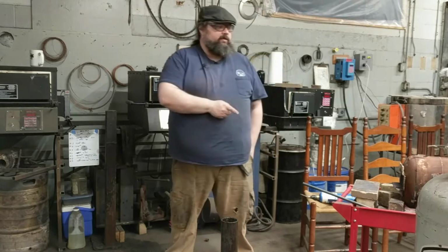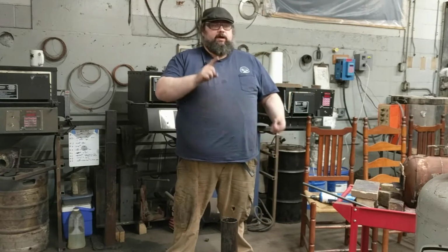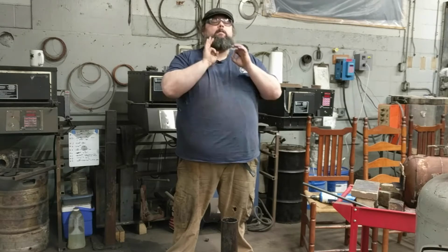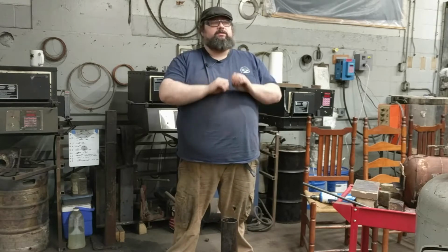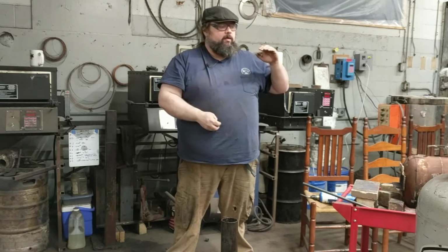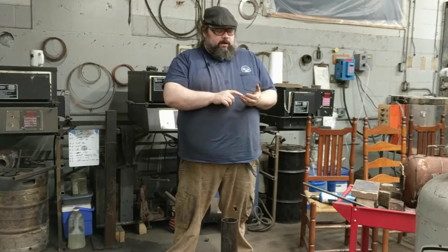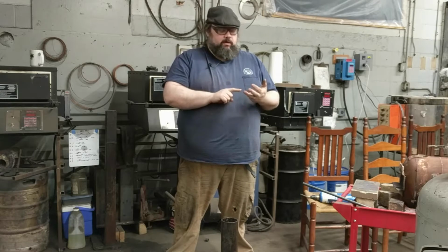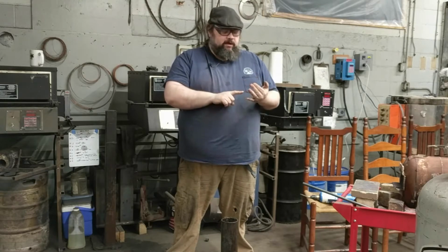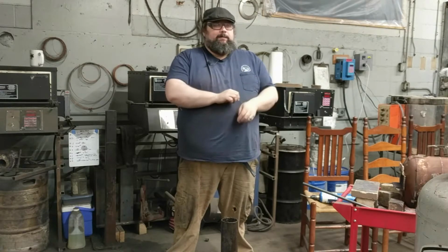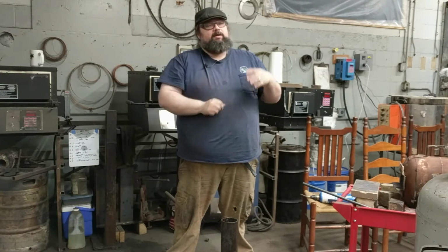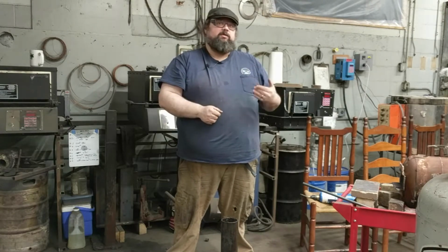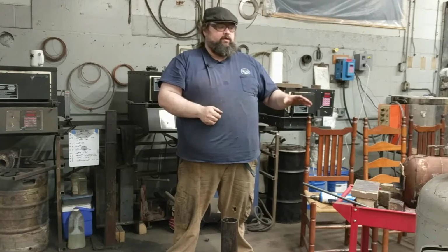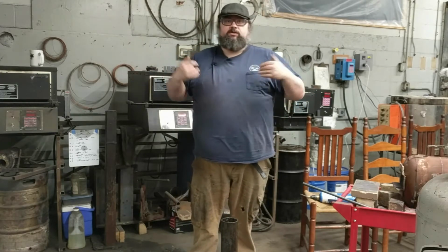Steels you want to stick with if you're going to heat treat in a forge: 1080, 1084, perfect. Those steels are simple heat treat, and they work amazing in a forge. Beyond that, you can do steels like 80CrV2 or 5160, 9260, and even steels that are pretty high carbon but have a very simple chemistry. Things like W1 or W2 can be done in the forge, although those steels do respond better to a kiln or salt pot heat treat.